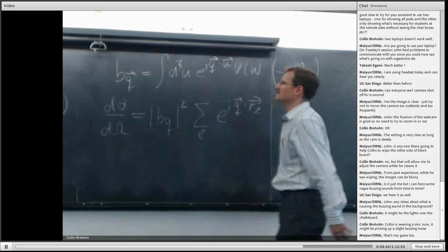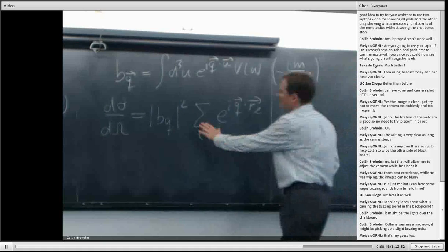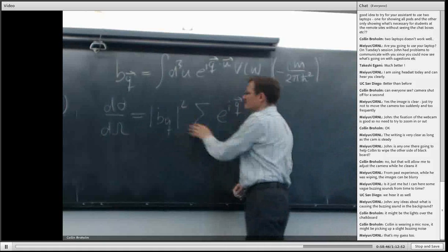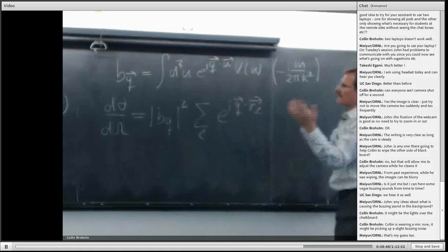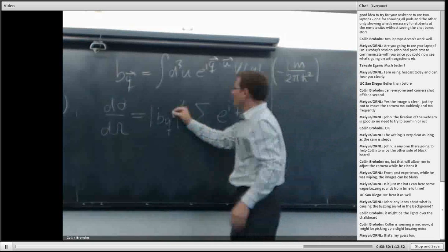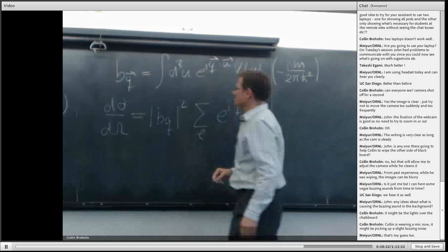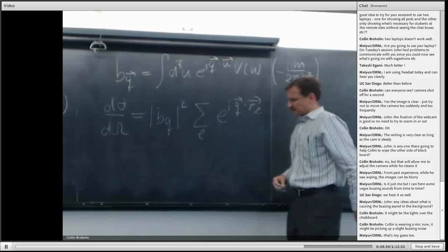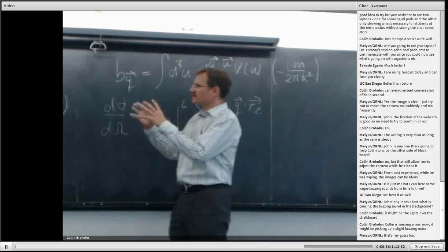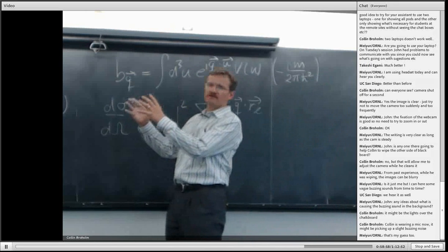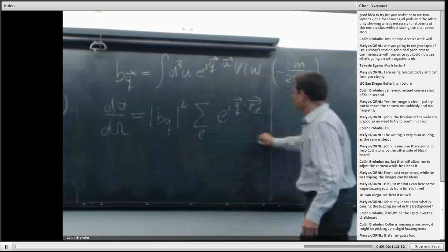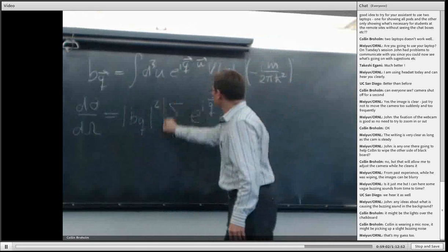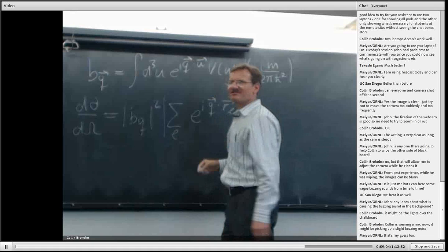So the consequence of having this repetition of many units in my material is going to be an overall prefactor, which we could call, and which in many cases will be an atomic form factor. So it basically has to do with the Fourier transform of what I have within my unit cell, and then I have this famous lattice sum, which of course I should take the mod square of.